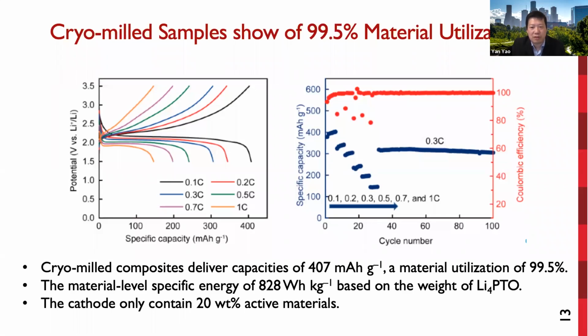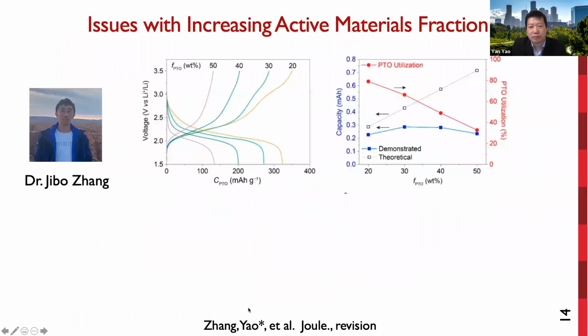At 0.3 C, it maintains 100% of its maximum capacity after 100 cycles. However, one remaining key issue is the low mass fraction of PTO in the cathode, only about 20%. So Dr. Jibo Zhang took the challenge to increase the PTO mass fraction. Jibo found that while increasing the PTO fraction from 20 to 50%, specific capacity decreased quickly. This corresponds to utilization from 80% to 32%.